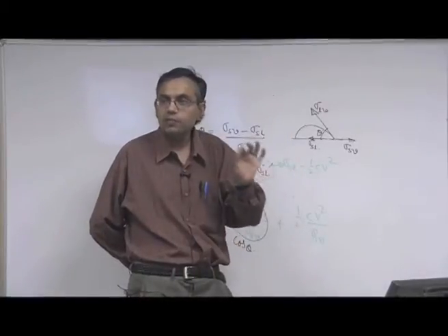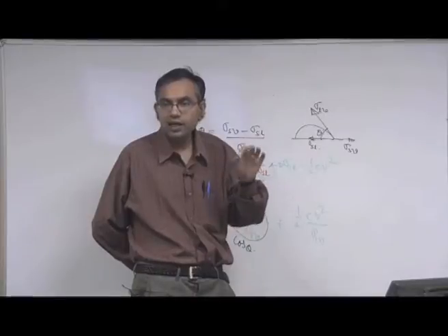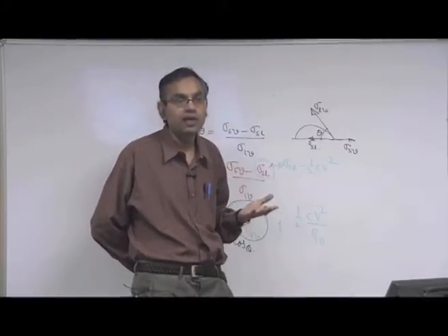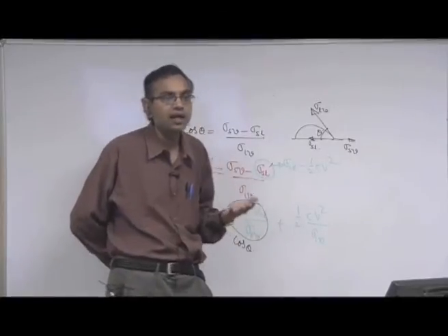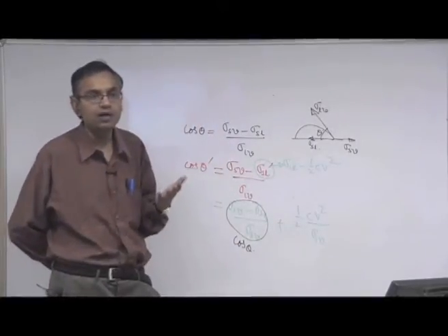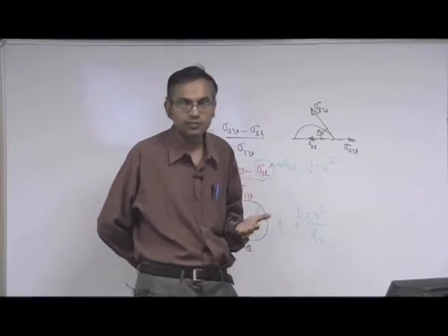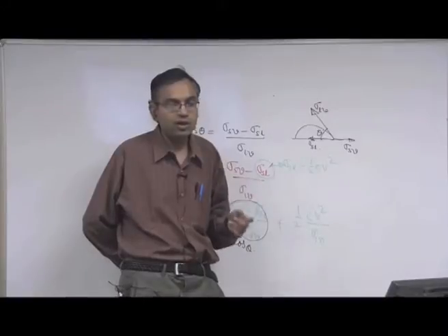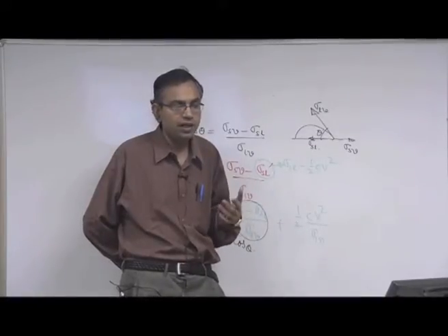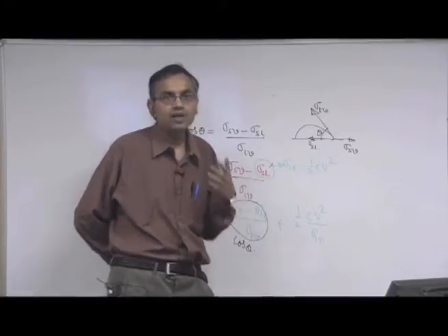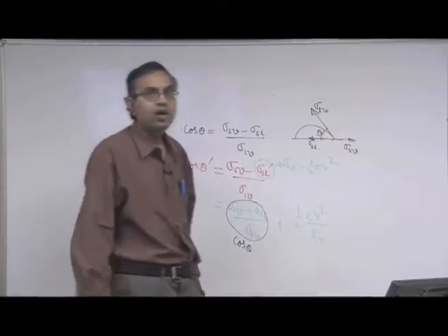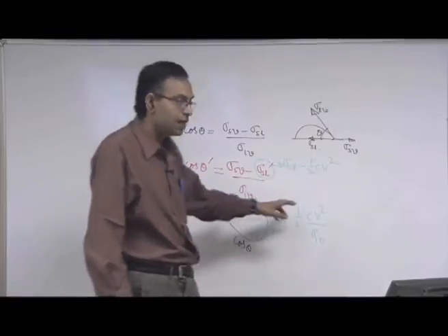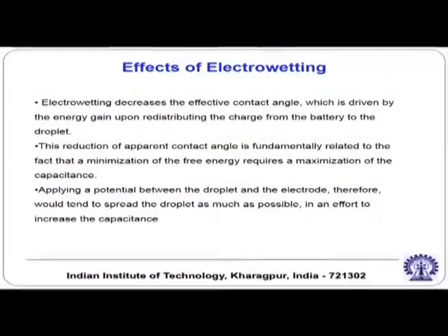That is possible on pen and paper, but in reality if you reduce the dielectric thickness beyond the critical thickness, there will be breakdown of the dielectric layer, it will no more act like a dielectric layer. So this phenomenon is called dielectric breakdown. So it is therefore common that you give a lot of importance to the voltage, but not so much importance to the capacitance for working with this technology.